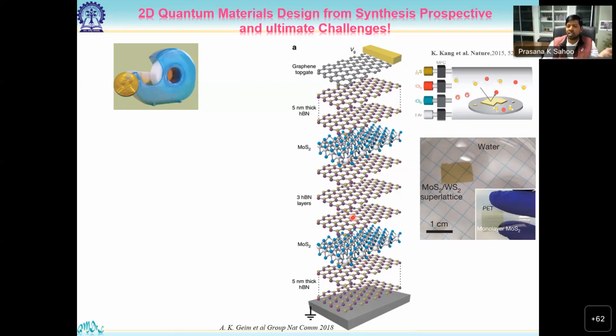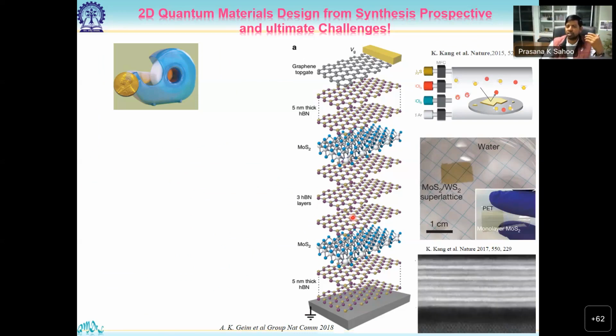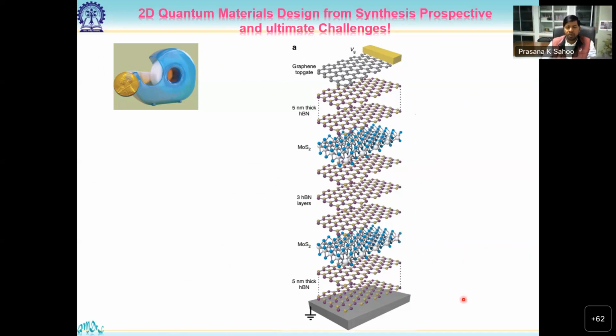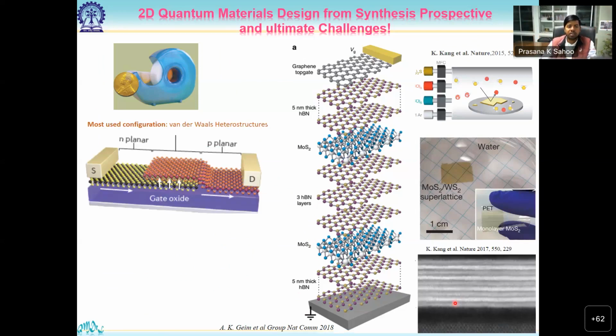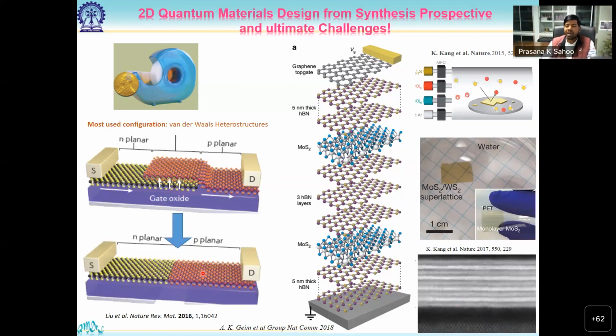Of course, there is recent progress to grow this kind of structure in MOCVD, where you grow individual materials, then stack them in this order. However, to make a perfect planar interface, mechanical exfoliation is not a solution. If you want a spatially separated PN junction heterostructure truly in the 2D geometry, in the quantum regime, you need to grow them directly. This is where we have made several progress in these directions.